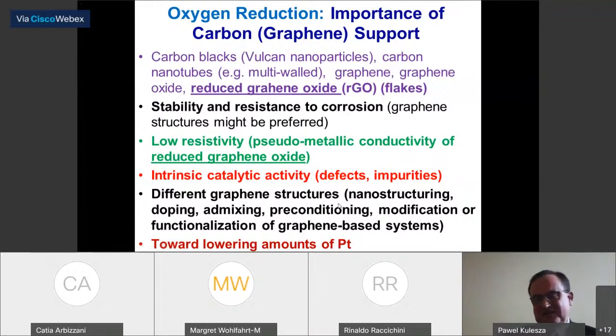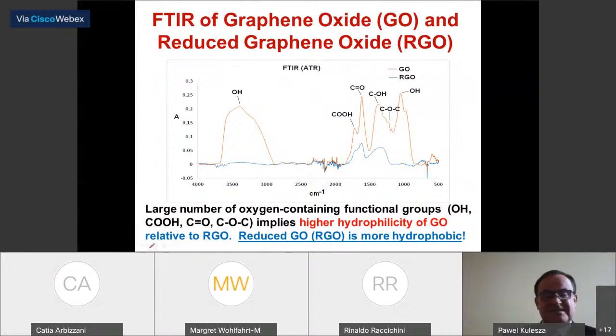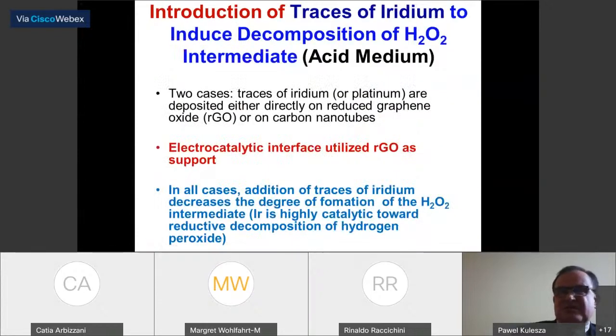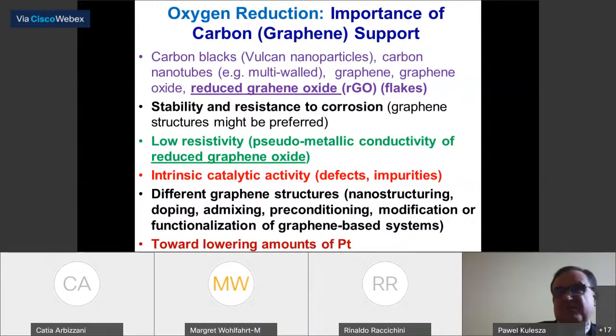So we use reduced graphene oxide. In fact, it was a part of Horizon 2020 first. And reduced graphene oxide is an interesting system. It's something between oxide with a lot of groups on the surface and, let's say, inert graphite. So it is more hydrophobic than graphene oxide, and lower hydrophilicity makes it more stable on the surface. The problem of the support is extremely important because carbon black is not very stable under practical conditions.